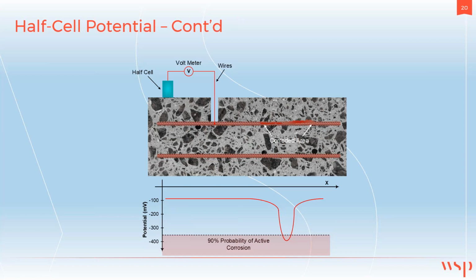It's only an indication of the potential for corrosion to exist. The test is done by having the half cell on the surface of the concrete above the bar, connected through a voltmeter, which in turn is connected directly to the reinforcing bar to create the electrical circuit. As you scan from left to right across the surface of the concrete, when you reach an area where corrosion becomes active, you see a sudden drop or increase in the negative value of the potential. Those are areas indicative of higher probability of corrosion.